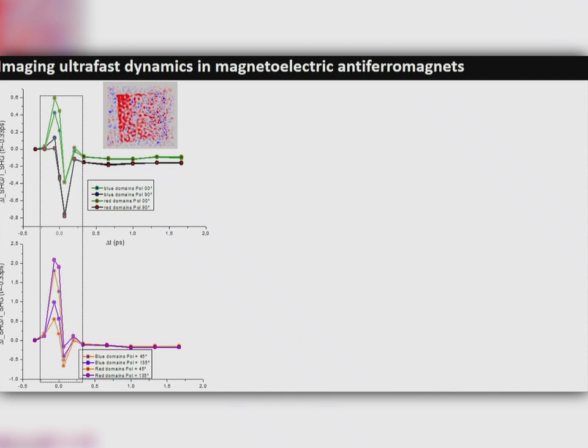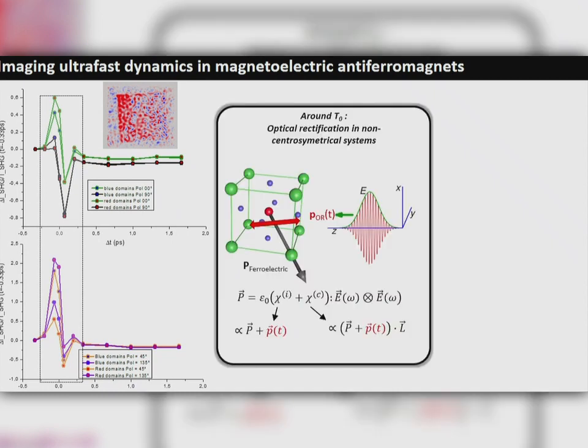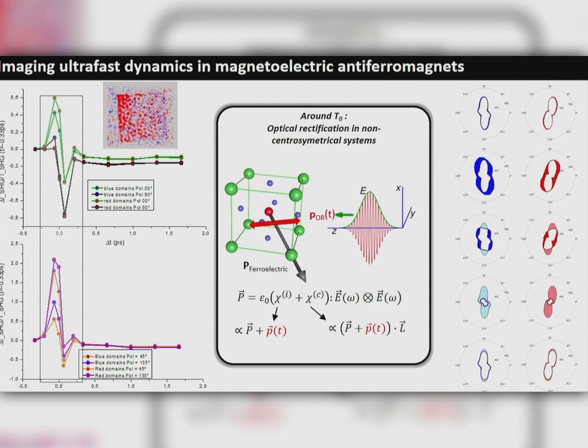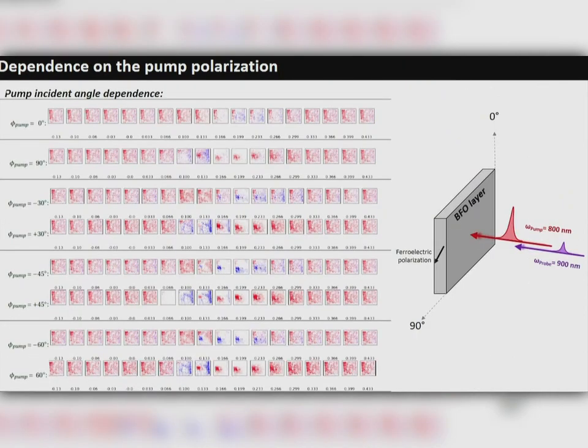The second thing is seeing what's happening around T0, where we try to understand if we can image this transient polarization. As I said, when the pump is on, we have this transient polarization, and we add a small contribution, and we come back to what I told you at the beginning about electric field-induced second harmonic generation. If you do that, you can look at how the angular dependence evolves and try to understand it. It's not so easy, because there are many contributions, but we would want to be convinced that optical rectification might be the process playing the main role. I will not ask you to look at the details of this image, but it depends on the pump polarization. If you go in one direction or the other, you can clearly see that there is a pump polarization direction dependence.